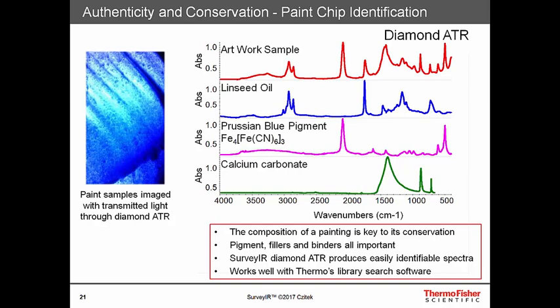This slide shows the power of infrared microspectroscopy in analyzing paints and their components. This is the linseed oil based paint shown in the previous example — a different paint chip observed through the diamond ATR. We can identify three different components: the binder is linseed oil, with its reference spectrum shown in blue; the Prussian blue pigment as indicated previously; and a filler, which is calcium carbonate. All of the chemical components identified in a paint are important to its conservation.